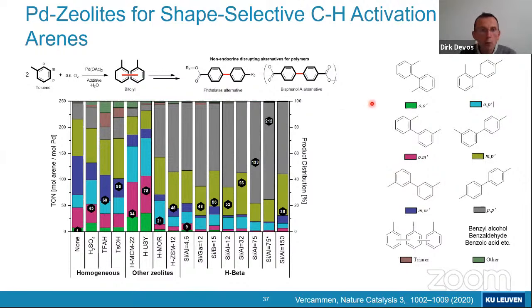Of course, if you couple two toluenes, and if you do that in a totally indiscriminate way, you can make 6 isomers, ortho, meta, para units. You see them all. And of course, it would be desirable to make at least one or several of these selectively. If you look at what, for instance, zeolite Y does with an adapted silicon to aluminum ratio, then you would see that actually zeolite Y does fine regarding activity, but you still make pretty indiscriminately, and actually even with some ortho preference, you make many isomers.